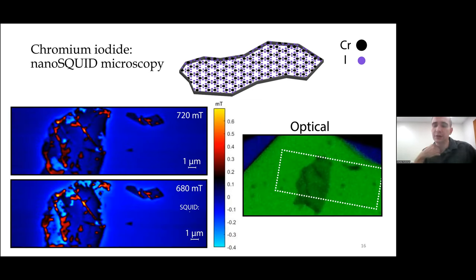So what I'm showing here is a four-layer chromium iodide flake undergoing an antiferromagnet to ferromagnet phase transition. There's an optical image of this region on the right, and on the left, you can see the nanoSQUID image. This image was taken with about an 80 nanometer tip, so it's about an 80 nanometer resolution image of the magnetic environment above the chromium iodide flake. And as you can see, there's some magnetic texture that's changing as a function of progress through this magnetic phase transition.